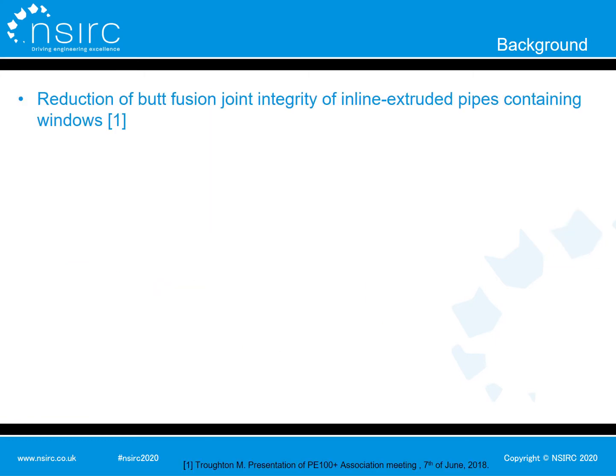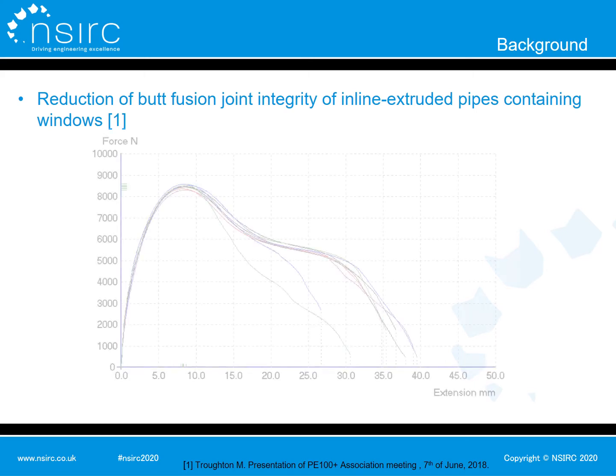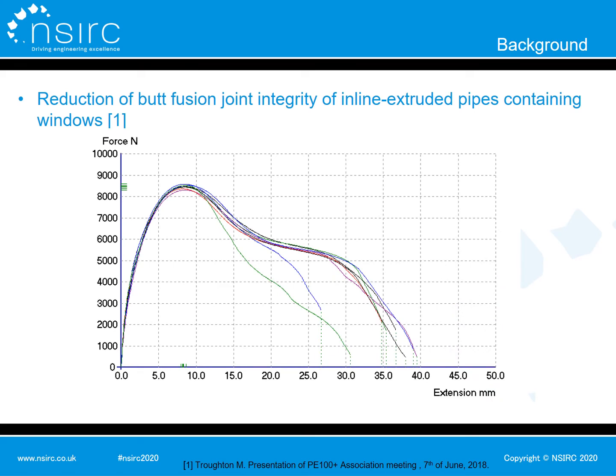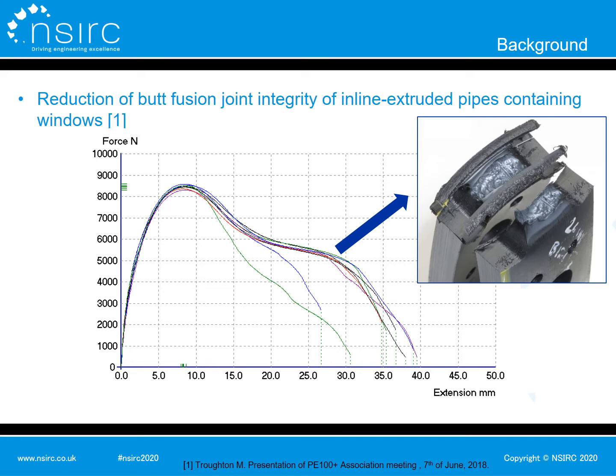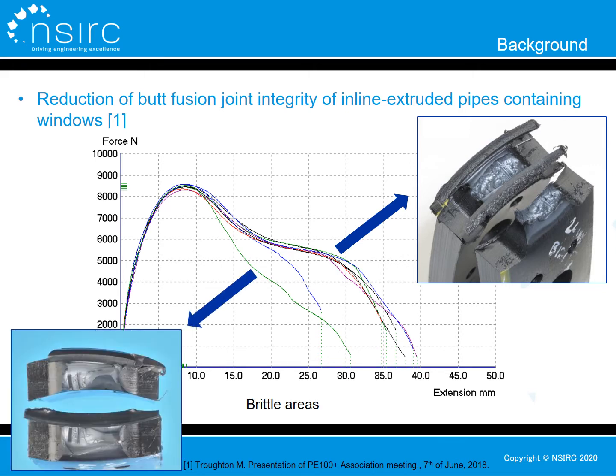TWI has done a study of the butt fusion joint integrity of polyethylene pipes containing windows and polyethylene pipes without windows. The tensile test specimens of the pipes without windows all fractured in ductile mode, with high extension to break and energy to break. The test specimens of the pipes containing windows fractured with lower extension to break and energy to break. Some brittle areas existed in their fracture surfaces.